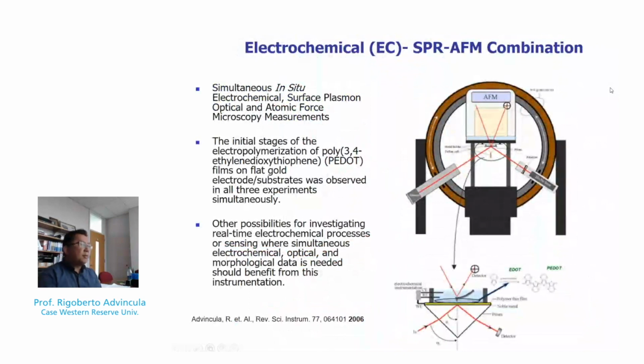Now, let me go this time to how we have combined electrochemistry, SPR, and AFM. So actually, this is a 3-in-1, 3 instruments in one, in that we were able to monitor the electropolymerization of PEDOT simultaneously while doing SPR, electrochemistry, and AFM. So this was possible because we use an open AFM system where we actually located it at the center of a theta-theta goniometer. So rotating these arms using a theta-theta goniometer means that we can do an SPR experiment.